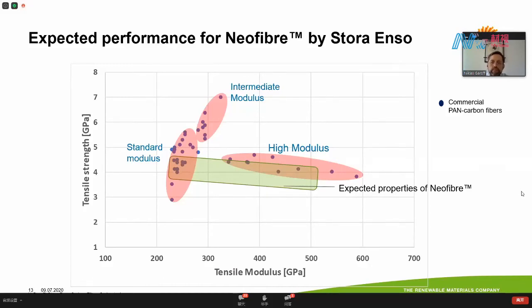And then we have another group called high modulus carbon fibers. These have moduli between 340 up to more than 600 actually. A bit lower tensile strength, and these are used for applications where you need very, very high stiffness, for example, robotic arms. Now, based on our lab scale results, we expect that our neofiber at commercial scale will have properties that are indicated in this green region.